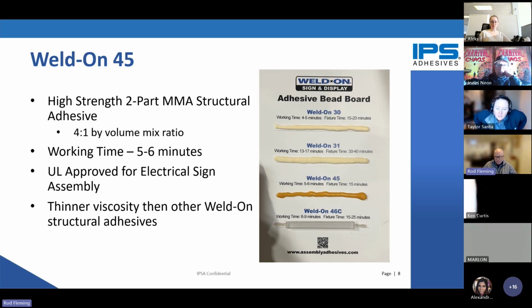An example of one of our structural adhesives, this being Weld-On 45, which is the workhorse in our product lineup. EM sells quite a bit of this across their customer base. This is a high strength 2-part methacrylic adhesive, very fast working time at 5 to 6 minutes, UL approved for electrical sign assembly. And this product has a thinner viscosity, say, than Weld-On 30 or even SG 800.